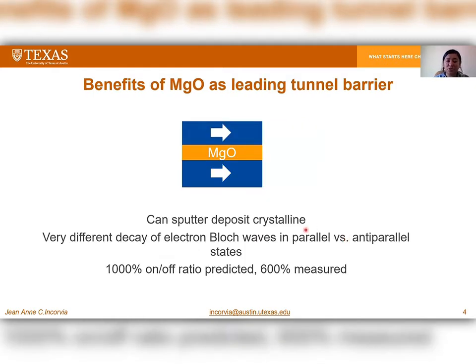There are several advantages to why MgO has been the leading tunnel barrier for decades now. When deposited, it's crystalline in nature, and it has very different electron Bloch waves in parallel versus anti-parallel states. Therefore, it results in a very high TMR, as I mentioned in the previous slide, of about 1000% in theory, and when measured, it was able to get up to 600%.